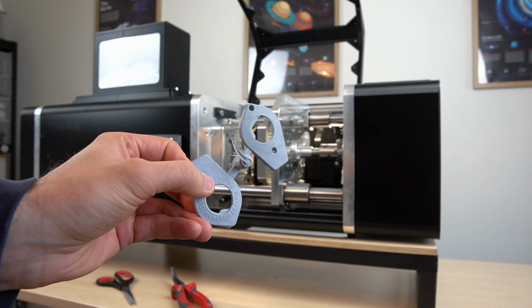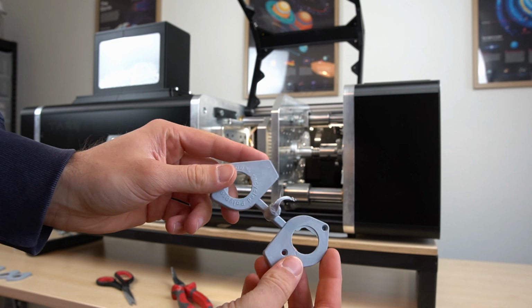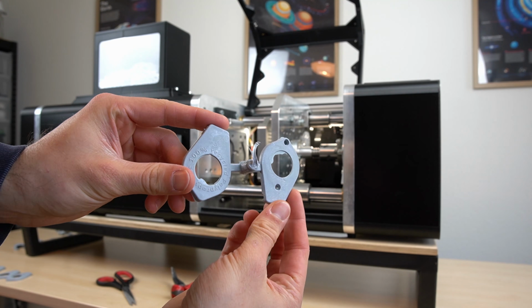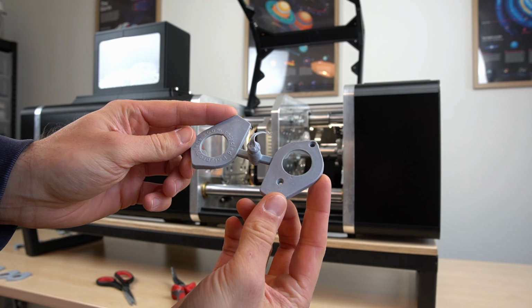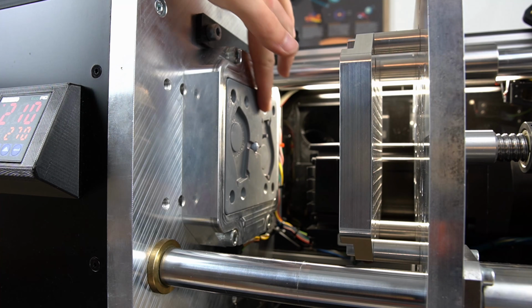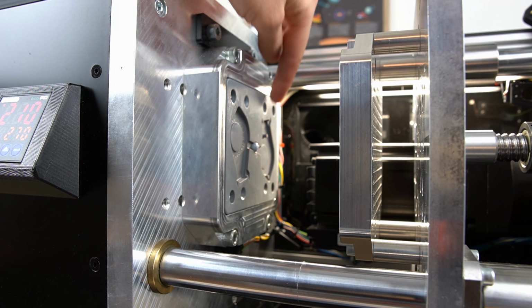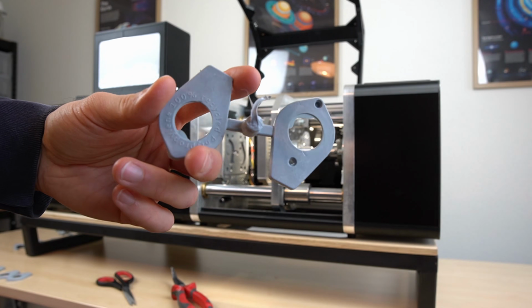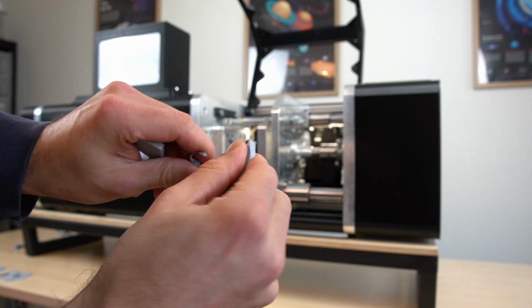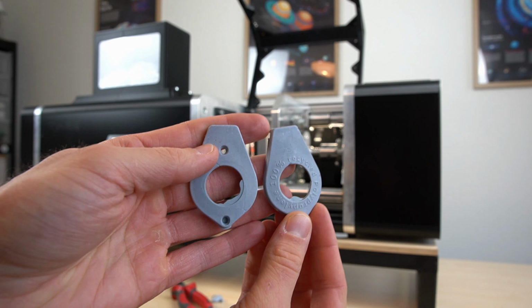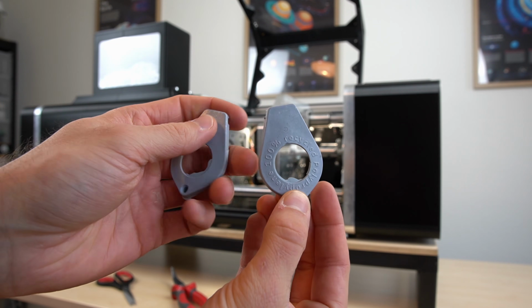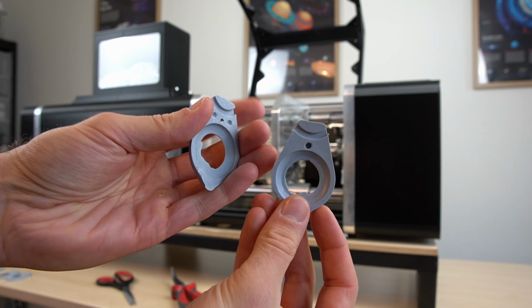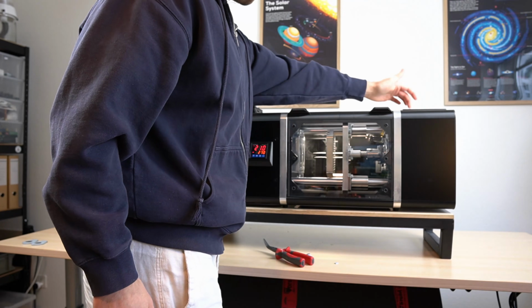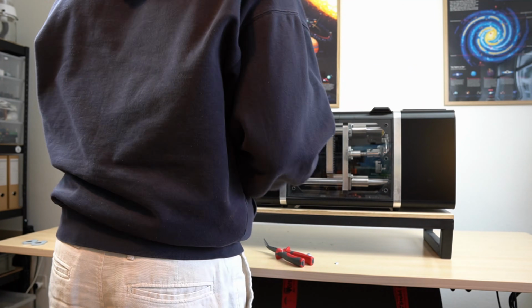Another thing I noticed with the resin mold is the lack of accuracy. These thin flashings that appear here are caused by the mold halves not fitting perfectly together. That always leaves a small gap, which then leads to these kinds of flashing. This is another point where material choice and a different printer, for example maybe a Formlabs machine with the 10K resin, could help. But with my current setup, that is definitely a limitation. A milled aluminum mold would be much more precise.